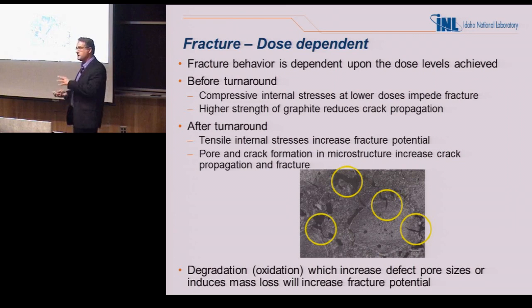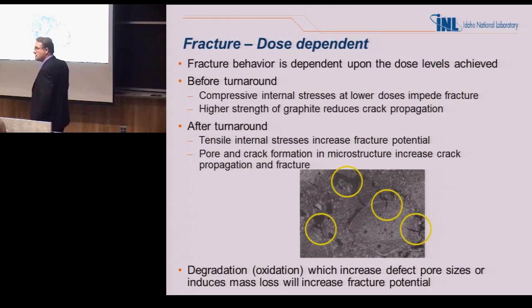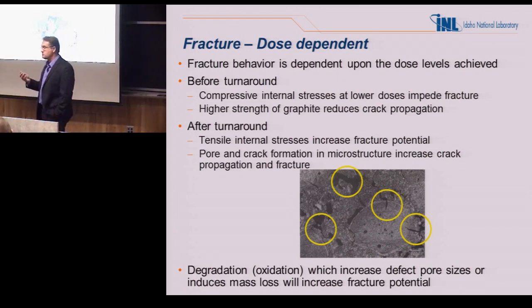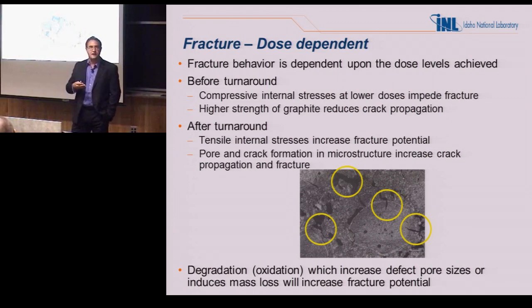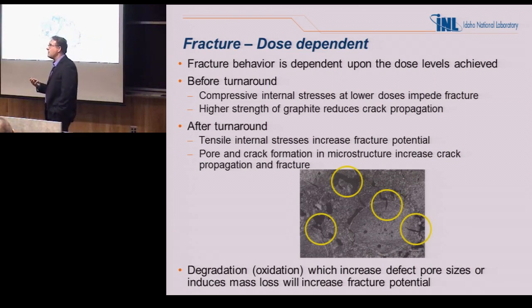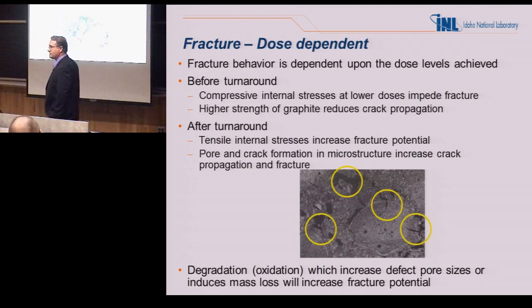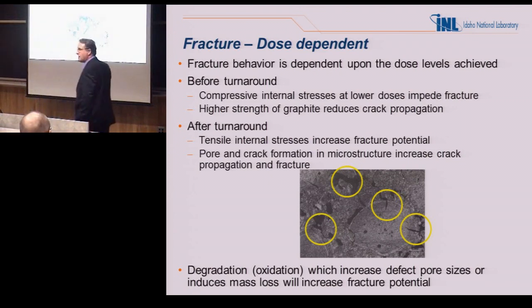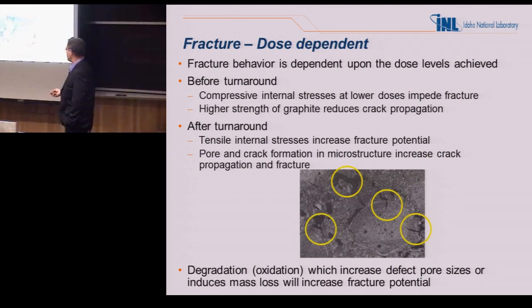After turnaround, now you've got tensile stresses occurring. You also have pore and crack formation, so you have crack initiation sites popping up all over the place. And plus, it gets weaker. So yes, graphite cracks after turnaround, and you can go and talk to the Brits right now, and the Brits can tell you, yes, indeed, their graphite bricks all have cracks, period. It makes for lively discussions with their nuclear regulatory system.